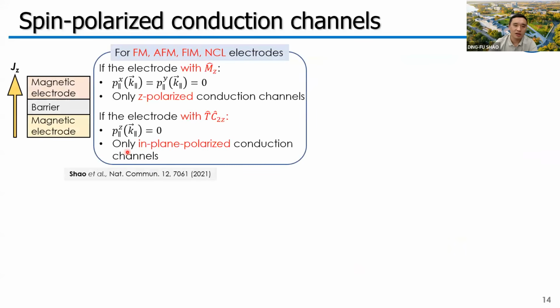We can further analyze the spin polarization of the conduction channels. If we consider the transport direction along the z direction, and the electrode has a mirror symmetry perpendicular to z, the conduction channels can only have the z spin polarization.